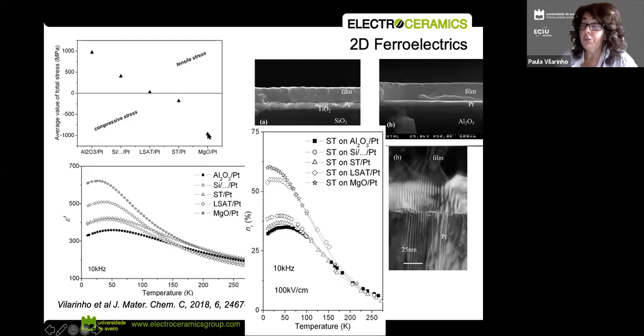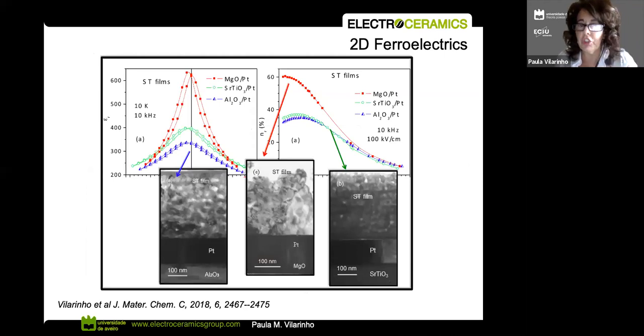So from that point of view, it's a very interesting example in saying we may have difficulties, but we can use them, we can leverage them. And that's exactly what is represented here. So these are the films on magnesium oxide. You see the microstructure, and here is the highest possible tunability. 60% is a very good value compared with the other films. And here you can also see the dielectric permittivity, that is the maximum. So the message here is we can use the difficulties to leverage advantages.